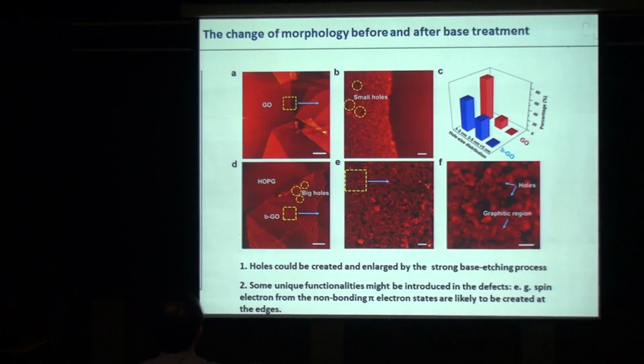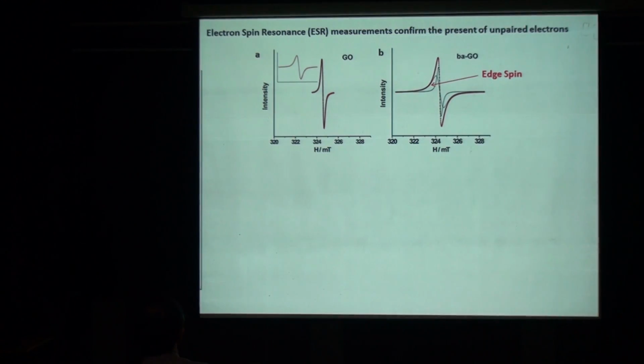Then the question is, how come? Why? Then we have to look carefully at this material. What happened during the chemical treatment? Well, this material is a crappy, defective material that the physicists will not want to take a look at. But you see, after the chemical treatment, it's highly porous, all the holes, defects have been generated, all kinds of holes. The more holes, the better for the catalysis, because the holes are where all the dangling bonds and spins are.